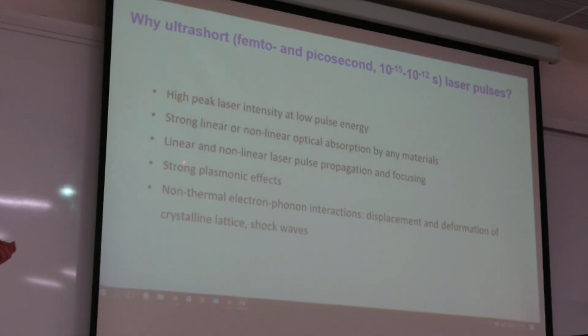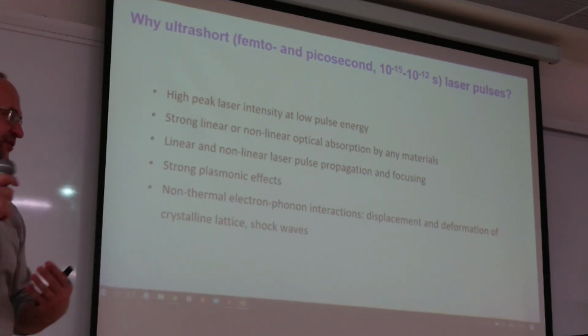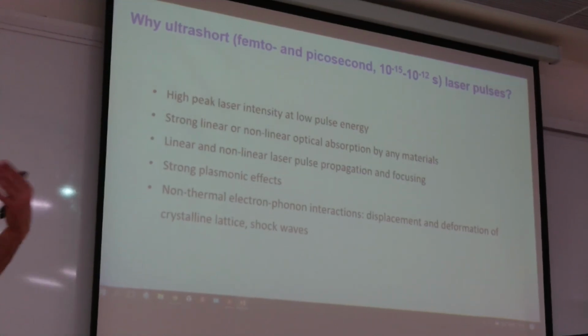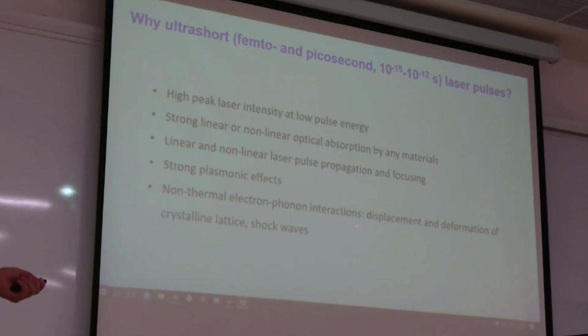Also, such pulses propagate not only in linear mode, like normal light, but also in non-linear mode. So they can be self-focused or defocused in transparent materials. Furthermore, there are strong plasmonic effects. If we produce plasma inside glass, we can also excite plasmons on such plasma, and plasmons can interact with light or with each other to make interference patterns on a very atomic scale. And finally, such lasers produce non-thermal electron-phonon interactions, displacement and deformation of the crystalline lattice, shock waves, and so on.